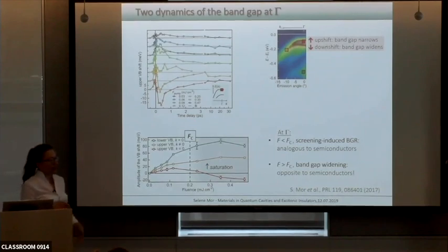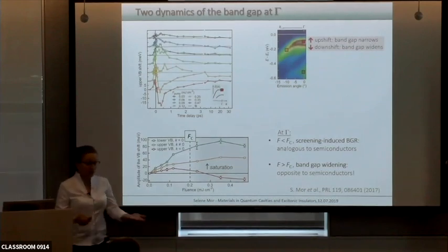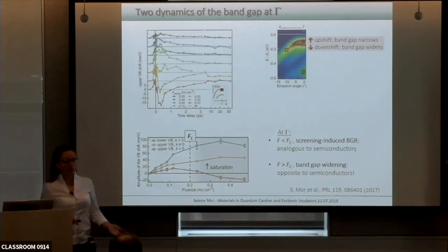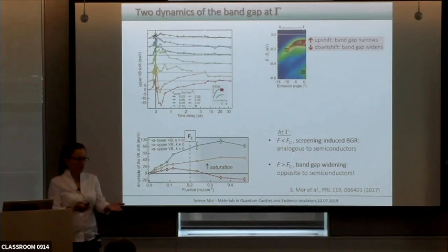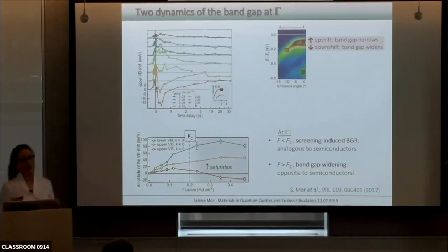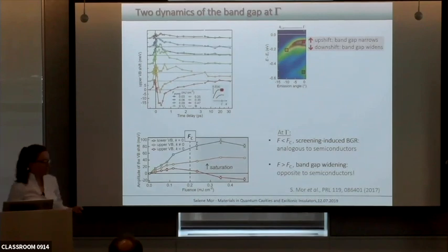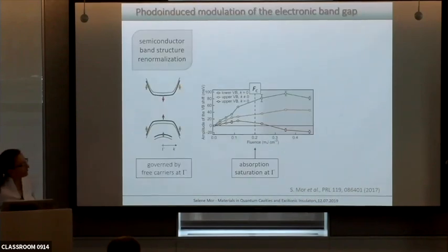And rather than speculating on how instantaneous it is, how instantaneous it becomes also depends on how much you are exciting, because the screening buildup that would be responsible for these dynamics depends on excitation density, and each material might have a different response. I would say the indication that this effect is fluence dependent points towards an effect related to free carrier screening. I suggest we could continue this discussion all night, but it would be nice if you could conclude it. Yeah, exactly.